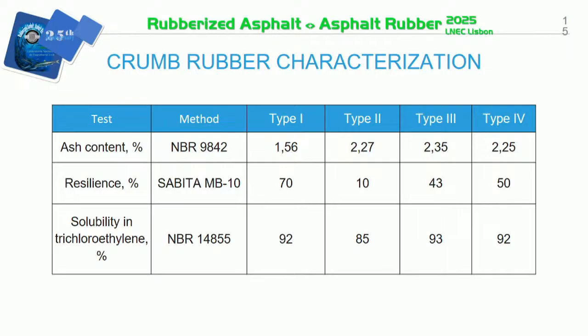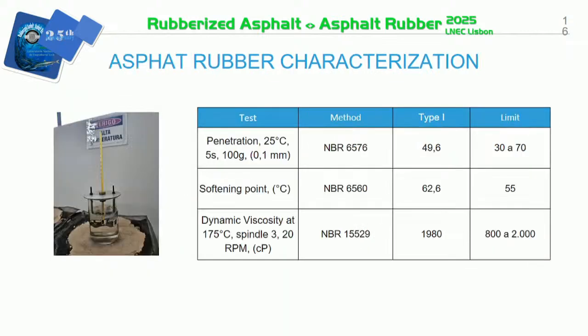Presented here are some of the results obtained after the dispersion and high shear mixing stages. The dispersal and solubilization of rubber in the asphalt binder were observed through several behavior changes, including an increase in softening point, a reduction in penetration, and an improvement in the elastic recovery of the binder.